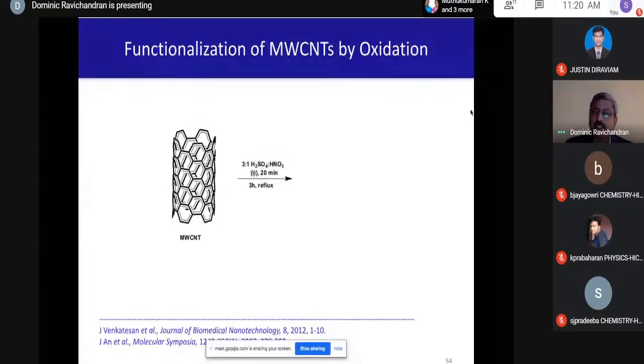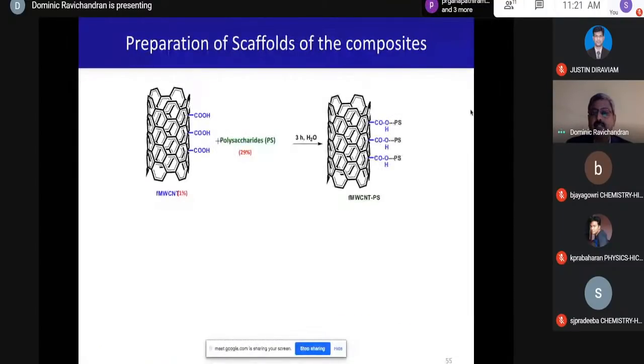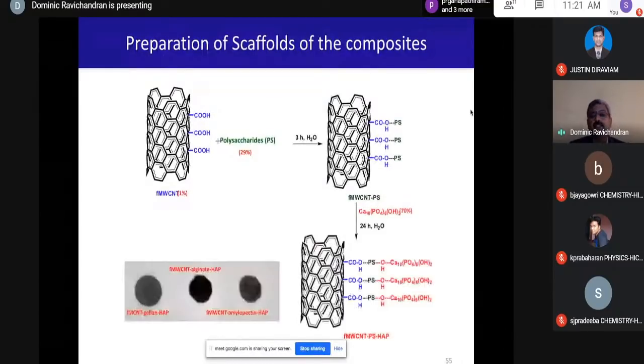In our case, we have functionalized the multi-walled carbon nanotubes by oxidation as indicated earlier. The multi-walled carbon nanotubes are functionalized by oxidation using an acidic mixture in the ratio of 3:1, and the conditions are as discussed earlier, to give the corresponding functionalized multi-walled carbon nanotube. The scaffolds are prepared like this: to the functionalized multi-walled carbon nanotube, the polysaccharides are added, and it is stirred for 3 hours, then mixed with hydroxyapatite.